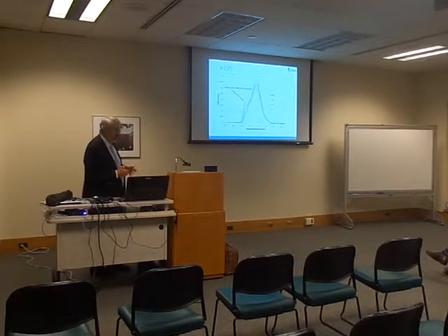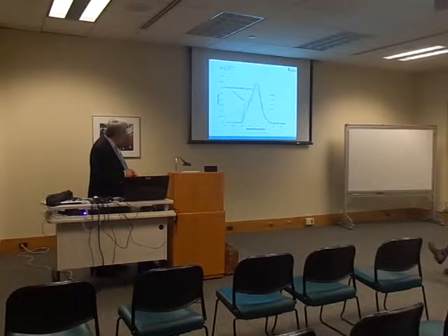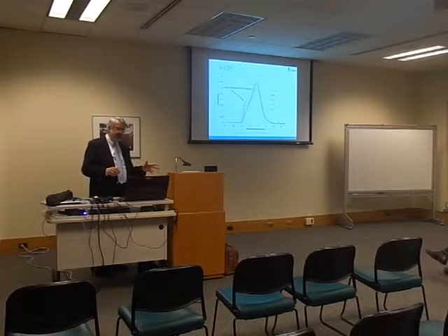The GPC is a particular technique which allows you to more or less gauge the distribution of molecular sizes in your material. And you notice that the blue one here is a particular aged bitumen, and as you go down, the drop really reflects the different amounts of aging that we can impose on this material. The less aged, the fewer large molecules.